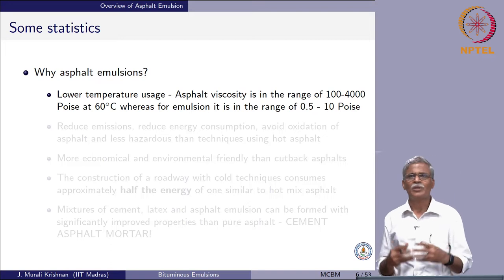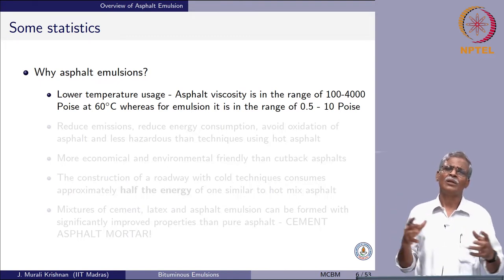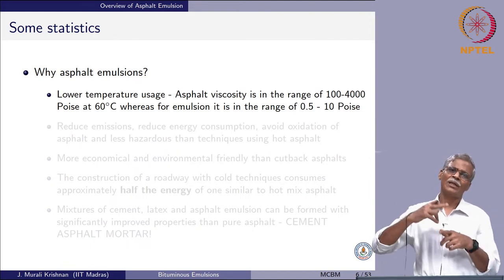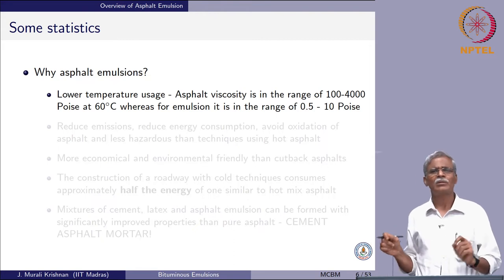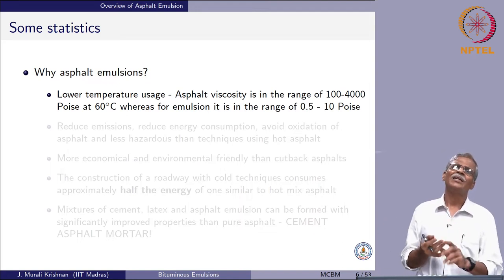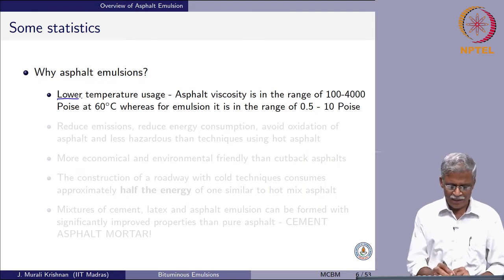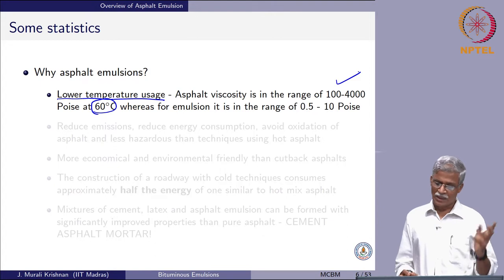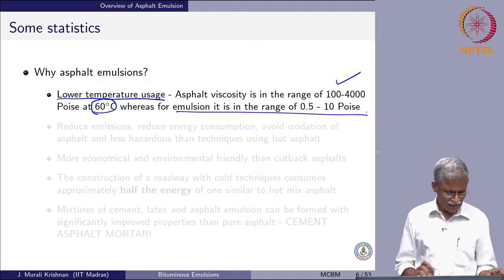Why do we really need asphalt emulsion? When mixing and compacting, you need to heat bitumen to a high temperature so it can coat aggregate particles. A smarter way is to make the bitumen flow at room temperature. At 60 degrees Celsius, viscosity is in the range of 100 to 4000 poise, whereas for emulsion it will be only 0.5 to 10 poise — clearly a game-changer.